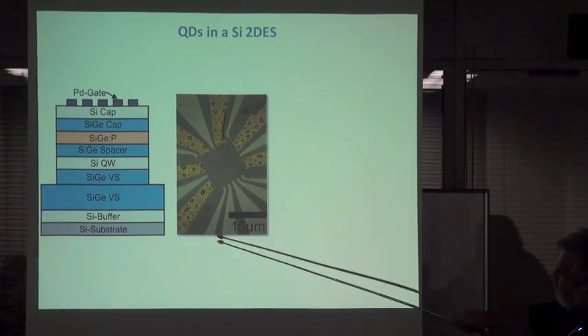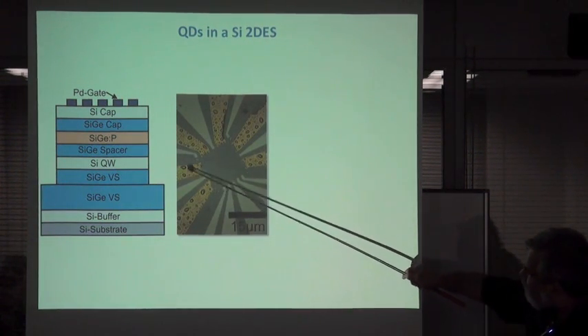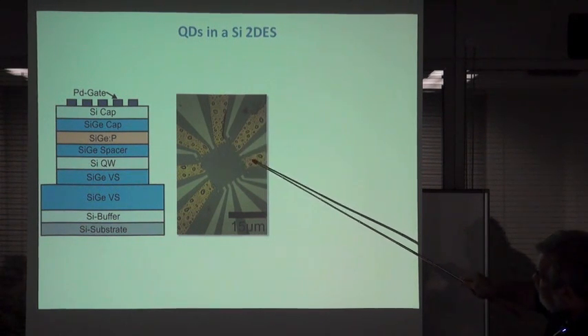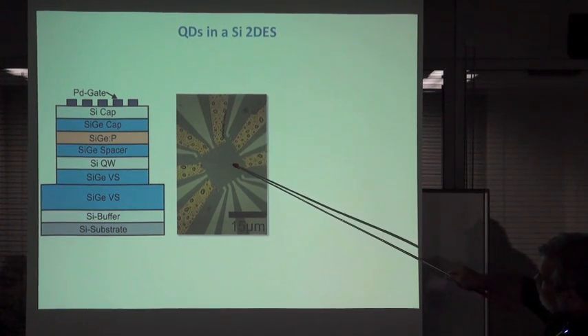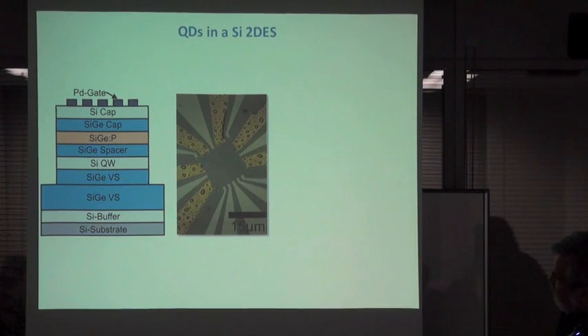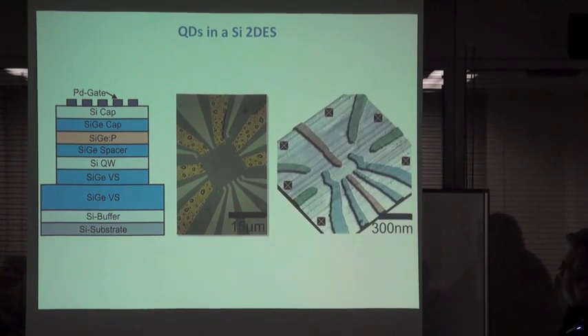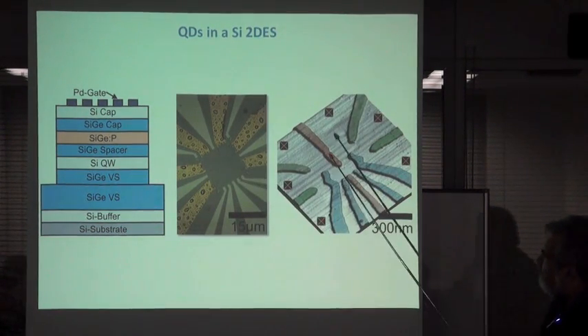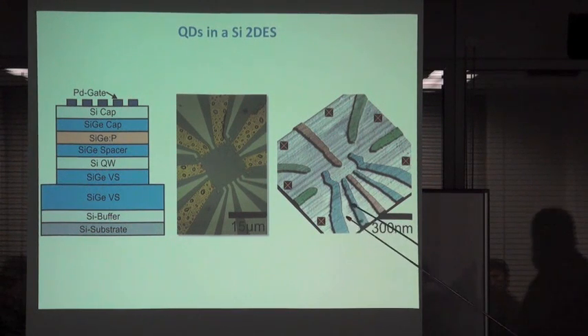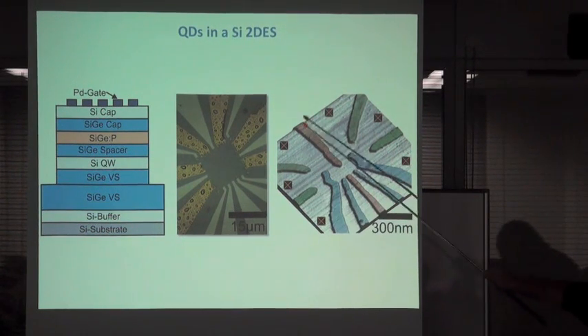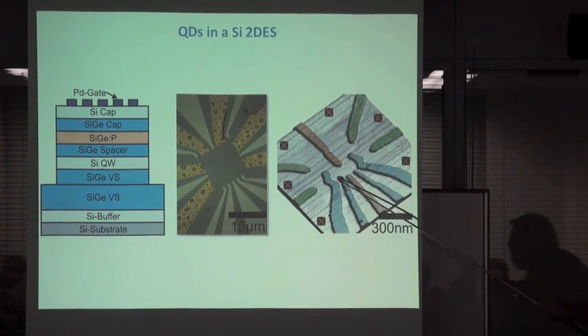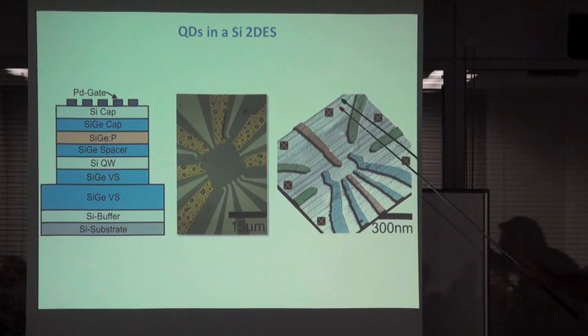And this is the layout of such a sample. These are the ohmic contacts with gold and some other material. In the inner part is the real sample, and these are gates. This inner part here is done by E-beam lithography, where you have here the ohmic contacts, and here you have the gate fingers, and here you define two quantum dots on top, and you have a charge sensor here, which can measure the charge in a dot.